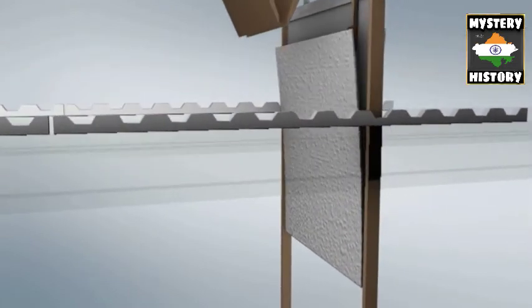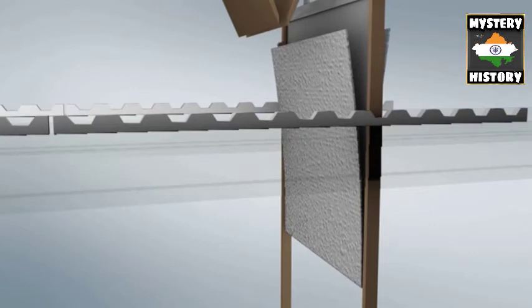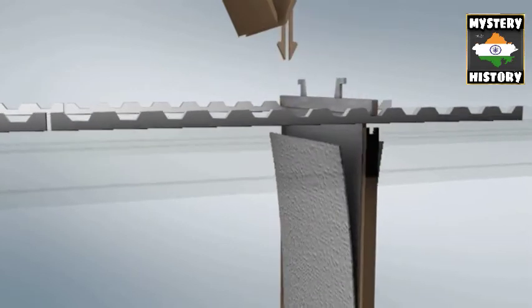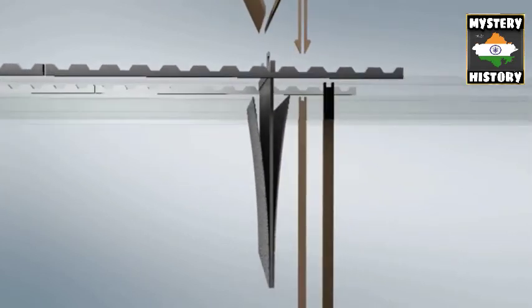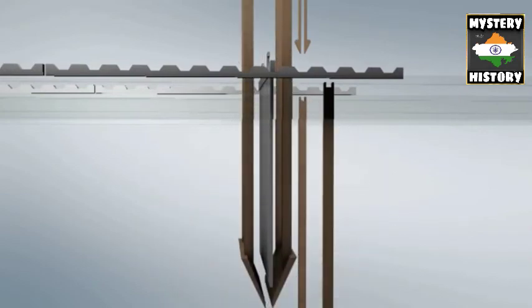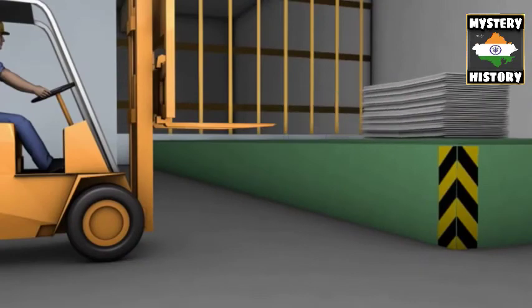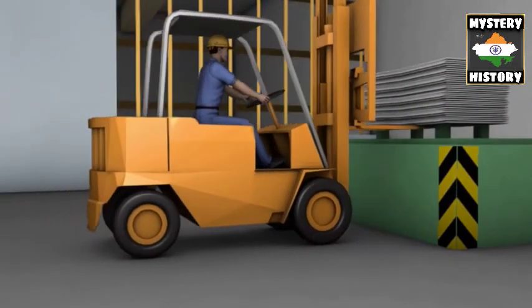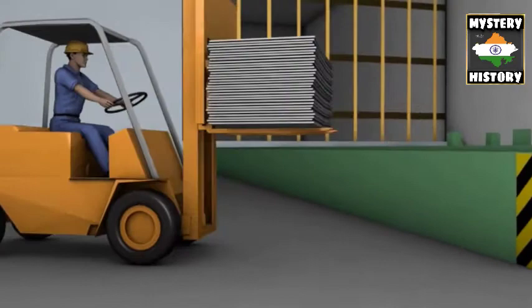The pure electro-deposited zinc is then peeled off the aluminum plates, washed, and transported to the melting furnace in the casting plant. The aluminum sheets will be put back in the electrolytic baths and reused to deposit more zinc from fresh zinc-containing electrolyte.